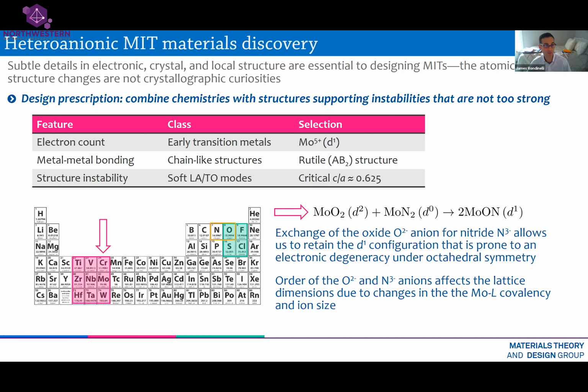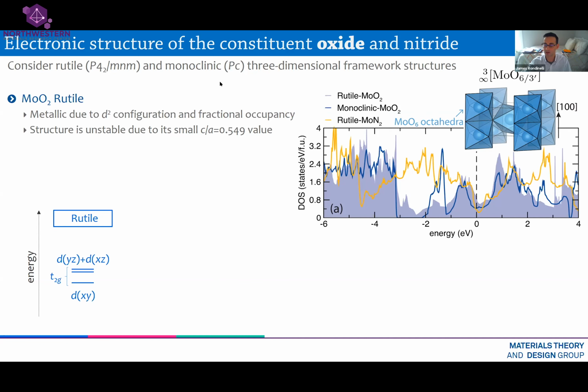And so one could go do this in the laboratory, try to synthesize this material and make the electrical measurements. But our approach then is to use this framework of density functional theory that allows us to abstract the equations that describe molybdenum dioxide and molybdenum nitride and to use them for molybdenum oxynitride and explore in advance of synthesis whether or not this compound will exhibit a metal-insulator transition. So that's what we've done. So we've done this calculation then for molybdenum oxynitride. And what I'm showing you now are some electronic structure results.